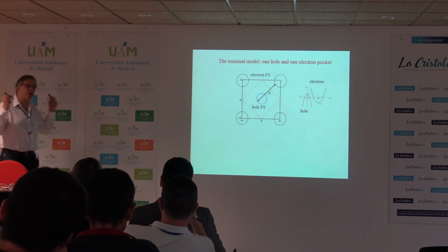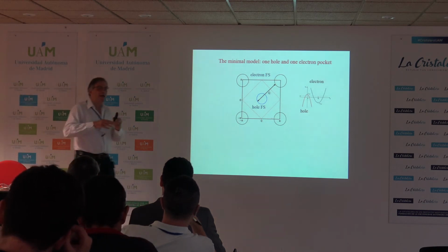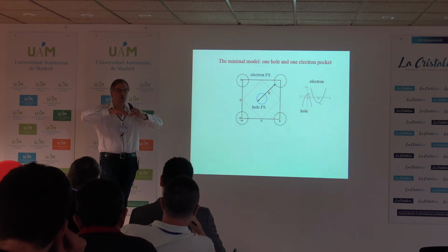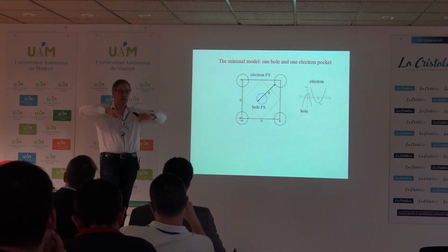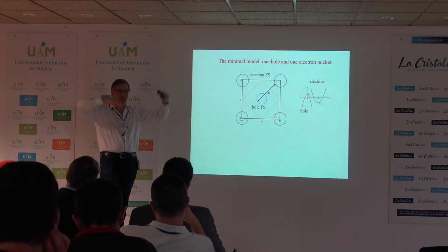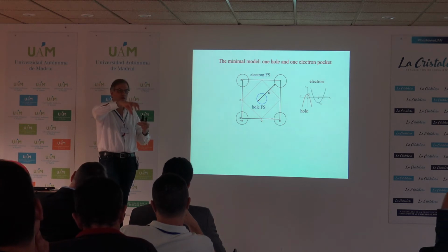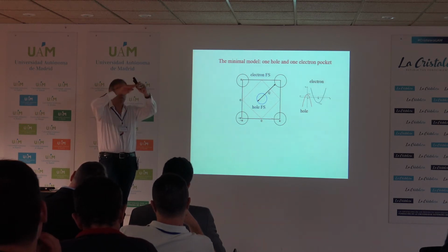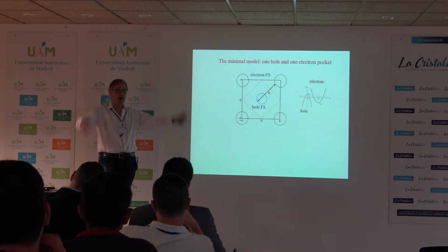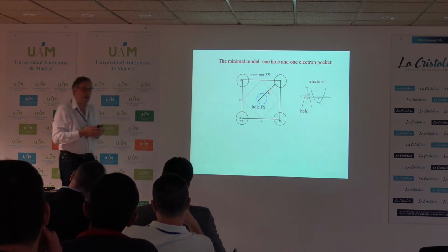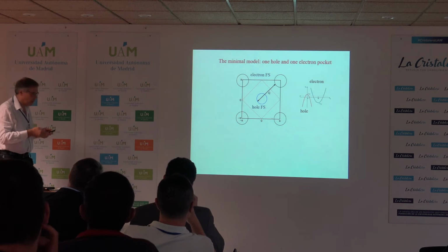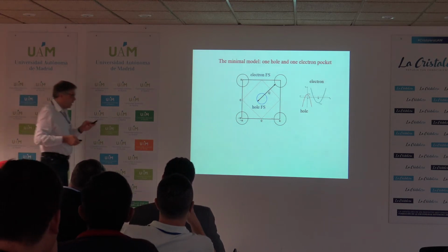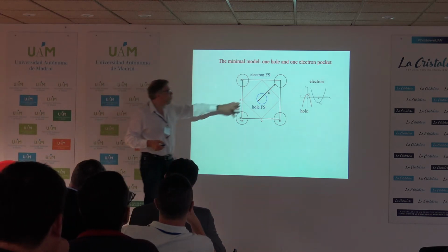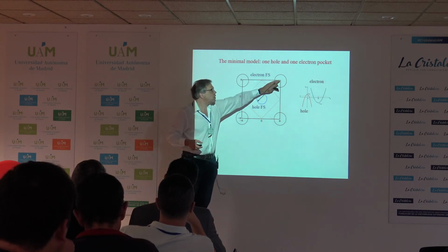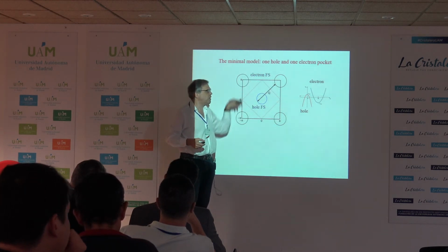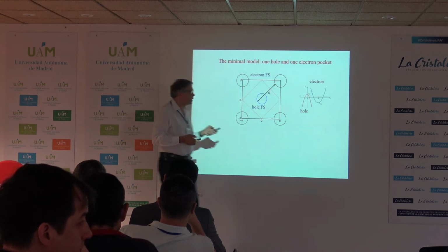I have electron pockets and I have hole pockets, which means what? I have regions where dispersion is conventional, meaning dispersion goes up and stays close to the bottom of the band, this is electron dispersion, or dispersion of opposite sign goes down and stays close to the top of the band. This is a hole pocket or hole dispersion. So if you take this and say, well, I have one pocket in the middle, one pocket on the corner, and all the 4 points are equivalent, so it's just really one pocket.